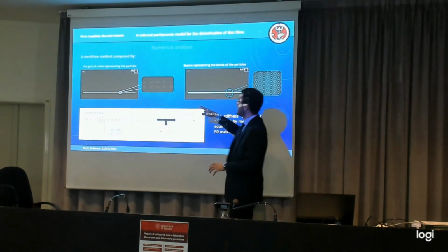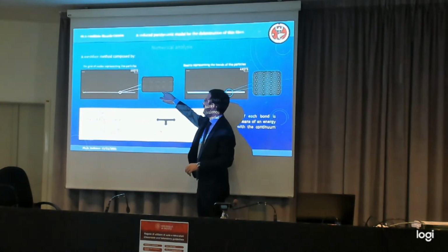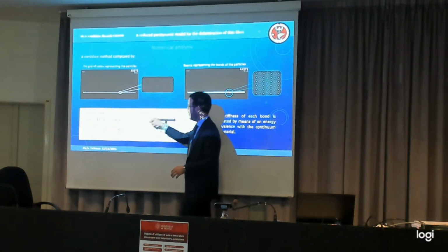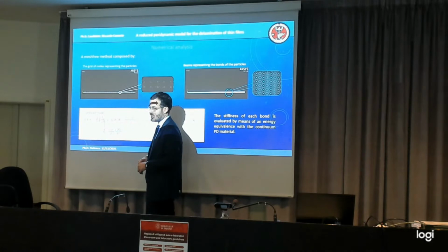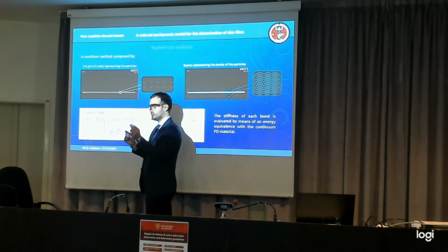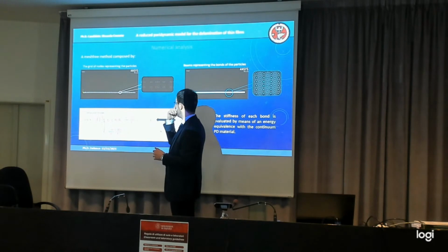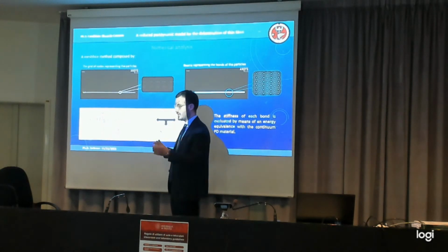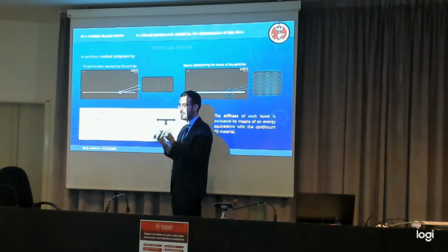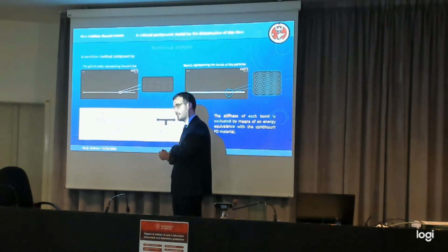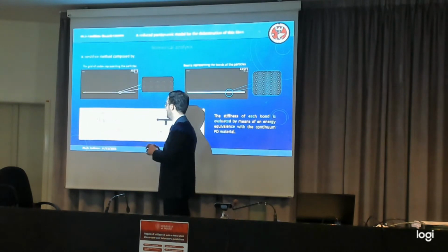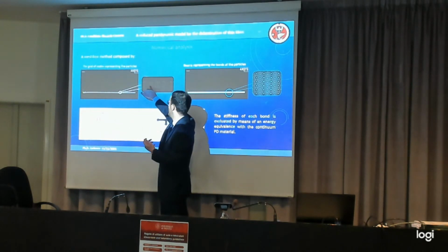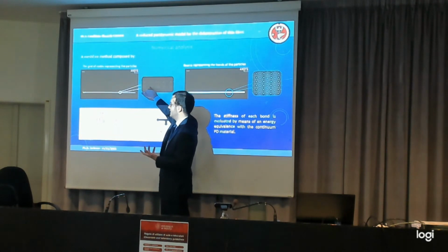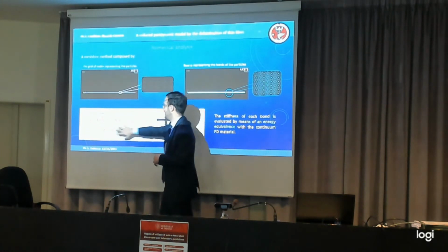Yes. The dots are nodes, and then if you take the dynamic formulation and you integrate the energy over very small volumes, because these couple of points have a force that are exerting one onto the other, which is dimensionally a force per unit volume squared. So you need two small volumes, and you integrate it, so you average the energy, and you obtain how much amounts the energy of a couple of particles. And this is the result.